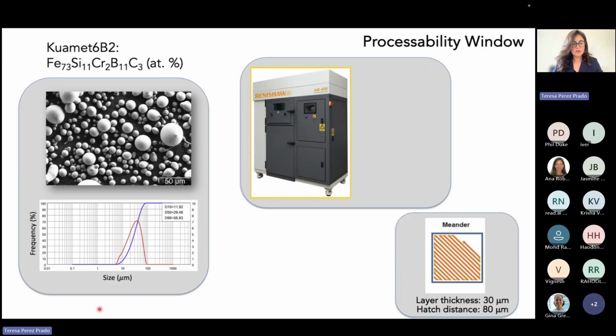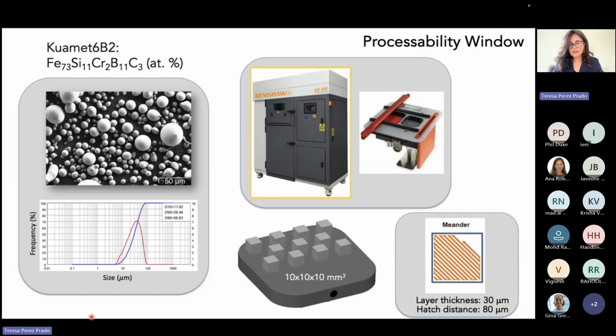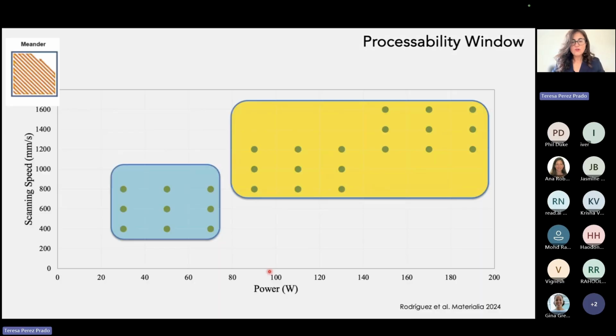And then we used our reducible volume platform that you can see here, because we said, okay, we are going to start printing simple geometry, small specimens, these cubes, which have 10 millimeters inside. So we fixed the parameters I just mentioned before, and then we explored the processability window by changing the scanning speed and the laser power over the ranges that you can see here.